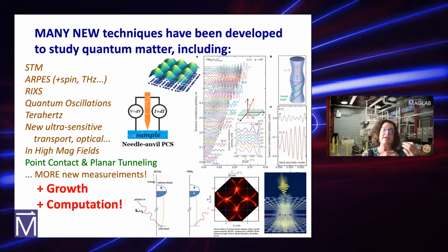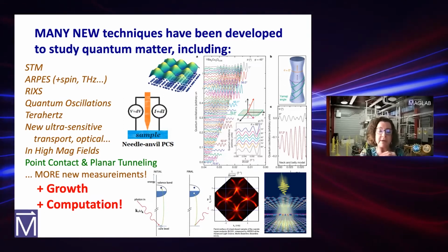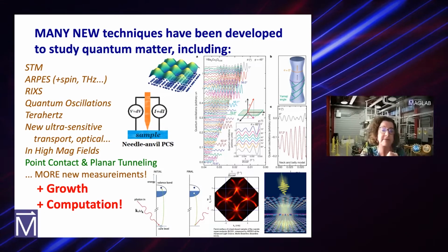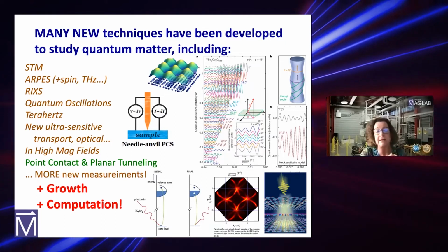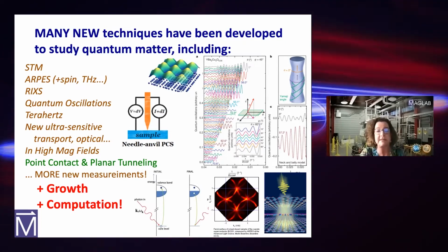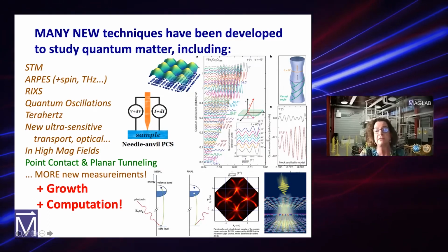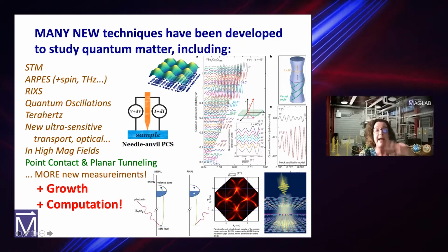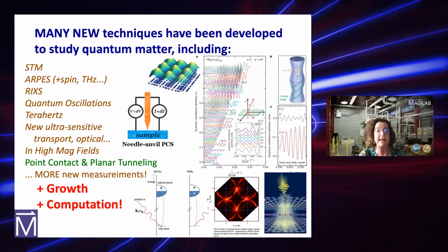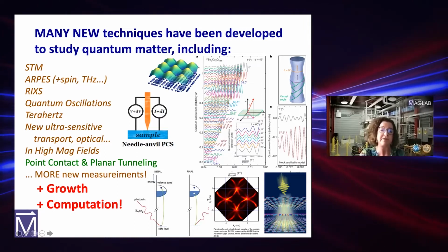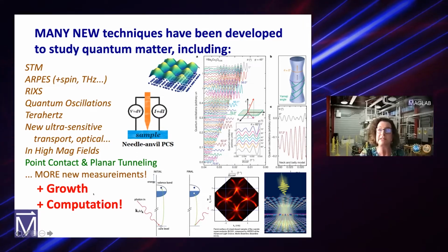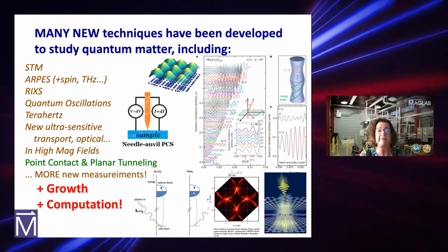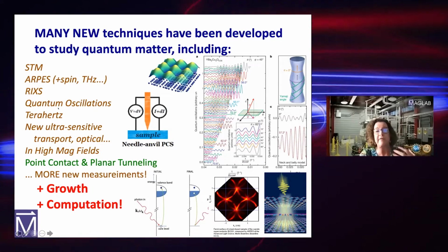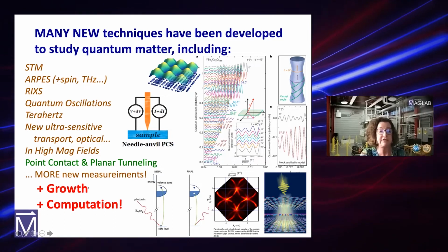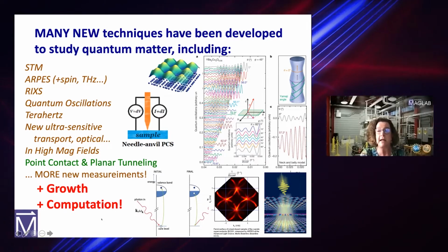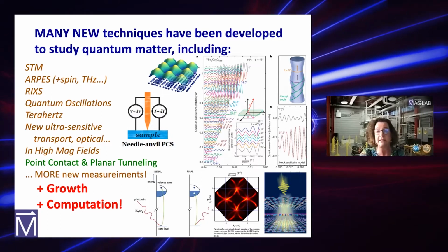And what's happened through the years is people have developed all kinds of intriguing measurement techniques: scanning tunneling microscopy, what they've been able to do with ARPES and resonant inelastic X-ray scattering, et cetera. Here's an example of quantum oscillations that was done several years ago in the Magnet Lab, where you map out the Fermi surface, and this would not have been possible without the much higher quality growth. It's been like a revolution in growth capabilities of these materials. You can pick out your favorite technique of measurement. Growth has seen transformation, and computation has also seen revolutions in what can be done.